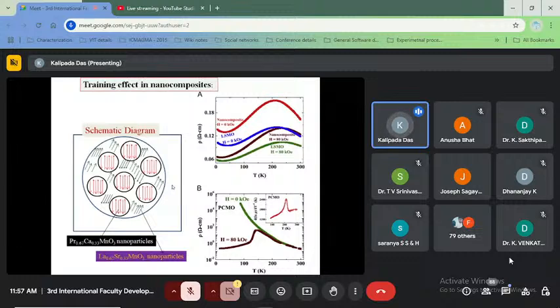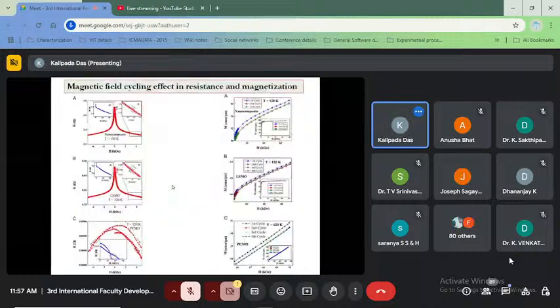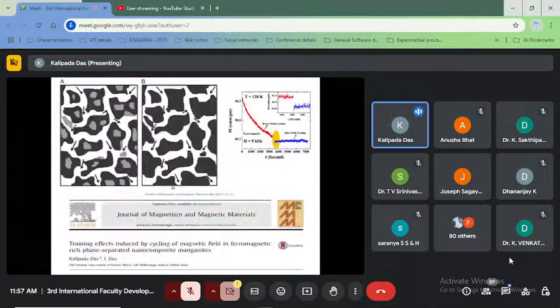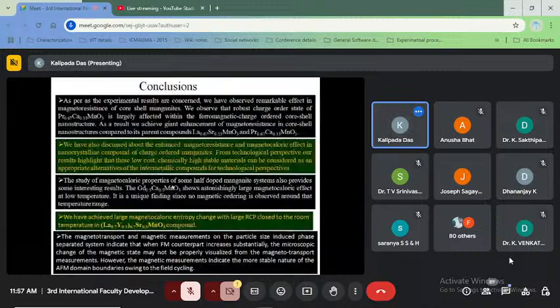Here the praseodymium calcium manganite is the core and lanthanum strontium manganite is the shell, just opposite to the first sample which I have shown, where lanthanum strontium was the core and praseodymium calcium was the shell. But here the situation is different. For this sample, we measured the magnetization repeatedly with cycling of the magnetic field, and we see that its magnetization value gets reduced with respect to the field cycling. This is called the magnetic training effect, which is also clearly visible in our phase separated sample.